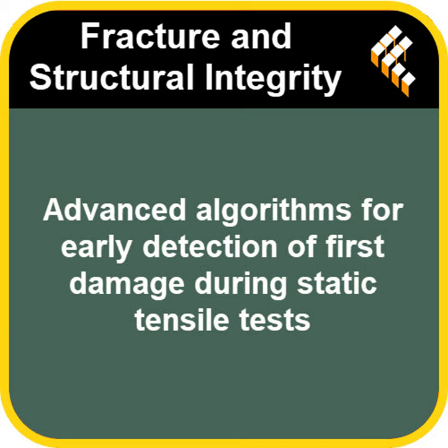Phase 2 is where it gets really interesting. The temperature trend stops being linear. It deviates. And this is crucial. It signals the start of irreversible changes inside the material, the very first microdamage appearing. During this phase, the temperature hits a minimum point right around the material's yield stress, where it starts to permanently deform. The point of no return, essentially. Kind of, yeah. And then phase 3, after that minimum, the temperature shoots up exponentially right until the sample breaks. That's driven by all the plastic deformation generating heat.